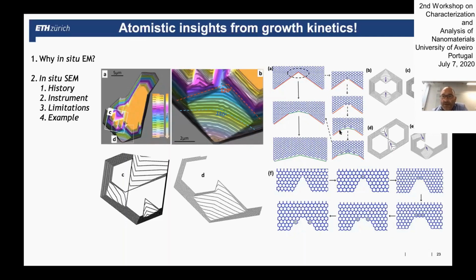And when you proceed like this, you actually form a specific growth front. It's the fastest growing growth front that has the highest kink density. It's this green one that comes at a certain angle. And with this one, you just grow very fast. And we did some image simulations, DFT calculations, and here are the simulations of what the experiment shows. And it all fitted precisely.